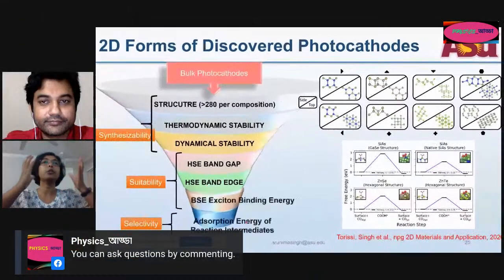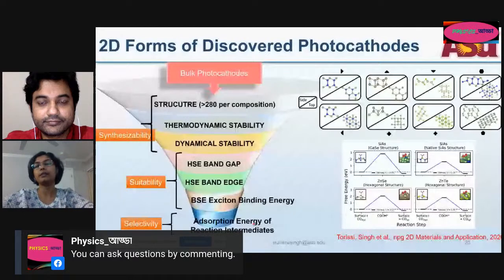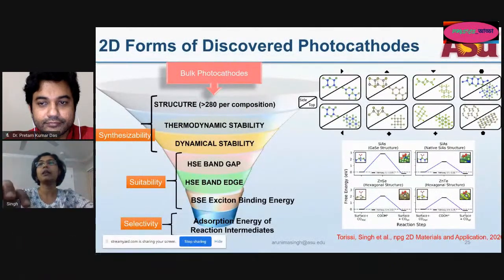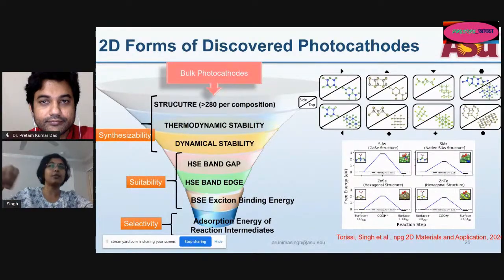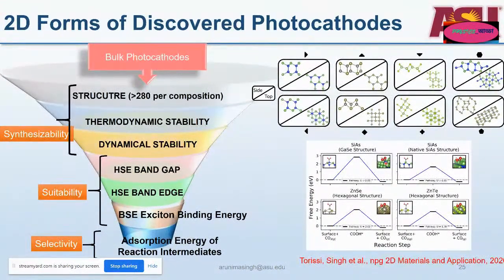And then we looked at suitability, which was given by the band gap and the band edges. Additionally, which we hadn't done for bulk materials and could do for 2D forms, we looked at their exciton binding energies and the adsorption energy of reaction intermediates. These two things are very complicated to simulate. For example, looking at the adsorption energy of reaction intermediates requires considering several intermediates and the different sites these intermediates could be on the surface. So we have to do a sampling of a huge surface.